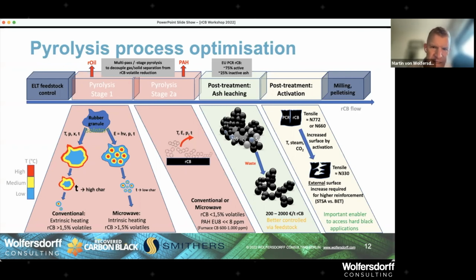Then ash leaching at the moment is not industrialized. Also, we have to think it's a surplus cost between 200 and 2,000 euros per ton of recovered carbon black to go from 20-25% ash to a couple of percent. The 2,000 is if you want 0.5% of ash. That you wouldn't really do for the tire industry. That would be quite cost prohibitive.